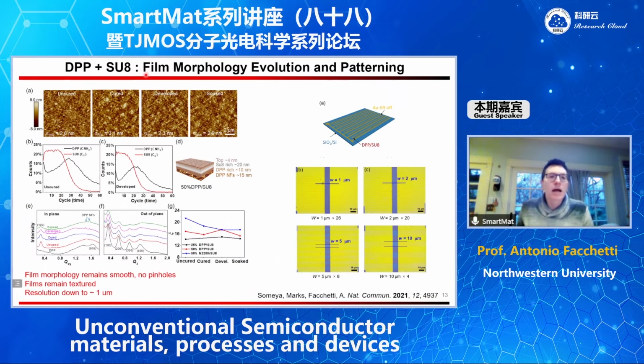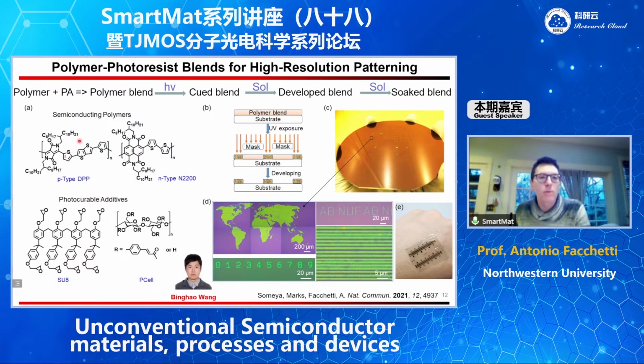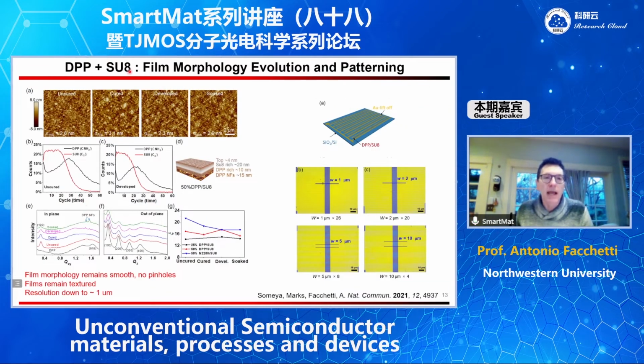And this is an example of a DPP, which is this first polymer, and SU8, the second photoadditive, blend. And this is the film morphology after spin coating, before curing, after developing, and after soaking. And you see here the morphology remains very, very robust, with very little variation in terms of topology. And these are some of the X-ray of the films. Again, here are the films: uncured, cured, developed, and soaked. And you can see here they retain the crystallinity of the DPP polymer. So basically it tells you that after curing of the additive, the film remains very, very robust, and somehow the semiconductor is embedded into the cross-linked matrix and remains very, very textured. And we can achieve a resolution on the order of 1 micron, which is more than enough to make back planes.